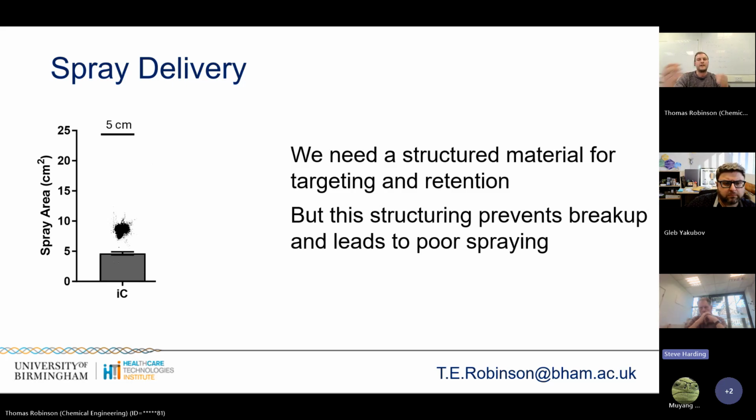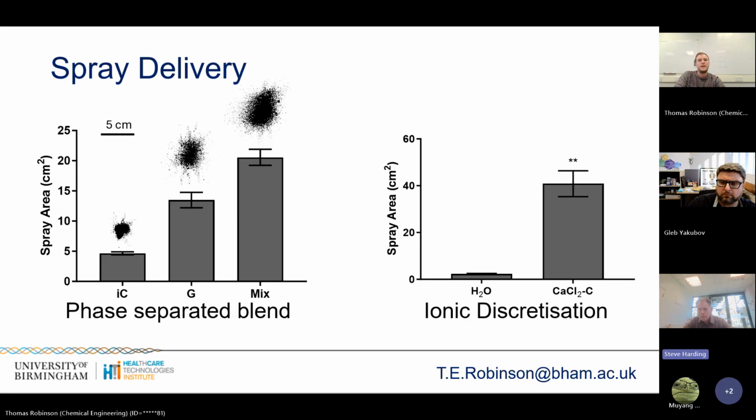So quite intuitively, I think you can kind of think about this as if you've got a completely entangled polymer solution. When you then try to disentangle it in a very short space of time over which the spraying process happens, it doesn't have enough time to disentangle and it doesn't break up. So you end up with quite a string, if you like, you don't get that breakup. So what we've been looking at is different formulation strategies to try and improve this.